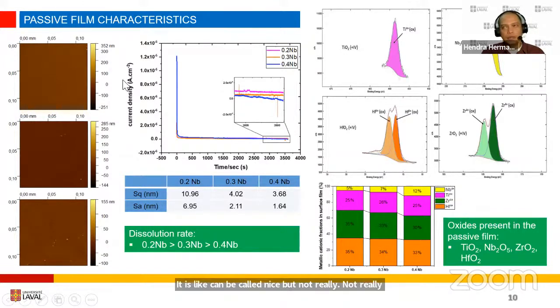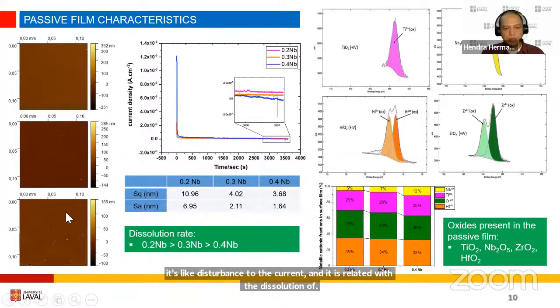So we monitor the current density over time, and we see some small activities, a disturbance to the current, and it is related to the dissolution of some metallic elements from the surface of our specimens. Okay,